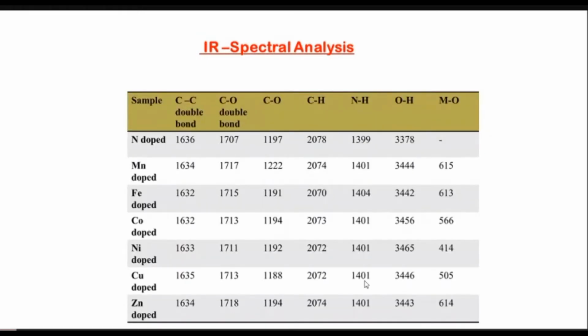From the IR spectral analysis, we get information regarding the functional groups present in the nanodots. This is the data we have obtained. We can see that most of the compounds show a peak in the 3400 cm⁻¹ range. It ensures the presence of OH bonds; these hydroxyl bonds ensure the solubility of carbon dots in water. In the co-doped transition metals, we can see a peak around the 400 to 600 range. It indicates the presence of the M-O bond, the metal-oxygen bond. It supports the incorporation of metal oxides on the surface of the carbon dots.